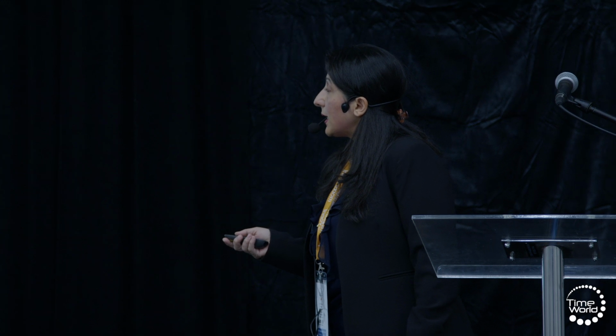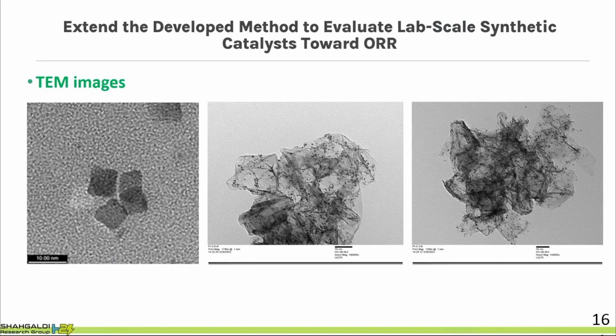The other work that we are running in the lab is, as I told you regarding platinum dissolution and detachment, we started producing shaped catalysts. For example, here, as you see, a cubic shape of platinum nanoparticle. Normally the platinum particles are round, and you don't have good attachment between your particle and your support. So we are producing shaped catalysts, like hexagonal or cubic shapes, in order to have a better connection between support and particle. This is one way. The other way is that we are working on the support material. For example, if you apply a metal oxide support, or a support that has better anti-corrosion properties compared to carbon material, it increases the durability of your catalyst layer.